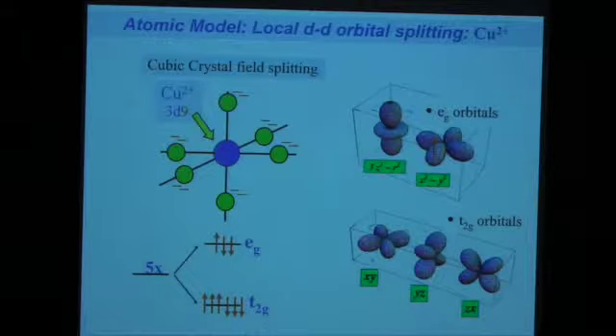So these are the t2g orbitals. They are all filled, these planar orbitals. The eg had 3 electrons or one hole. This elongated one, the cigar-shaped one, is filled, and the hole is in the x² minus y² orbital, which I've indicated here, the hole with now a spin. So that's where the hole is sitting.